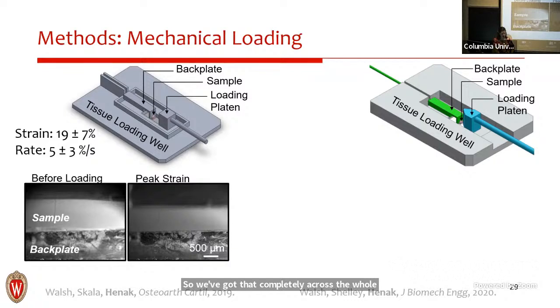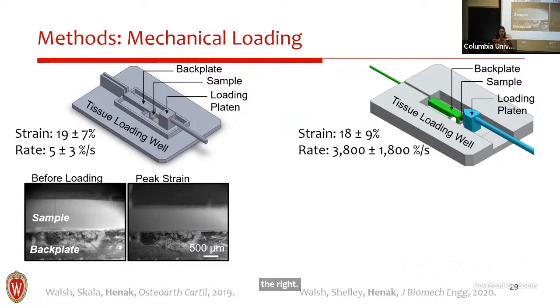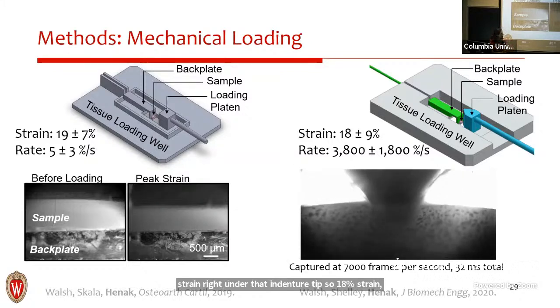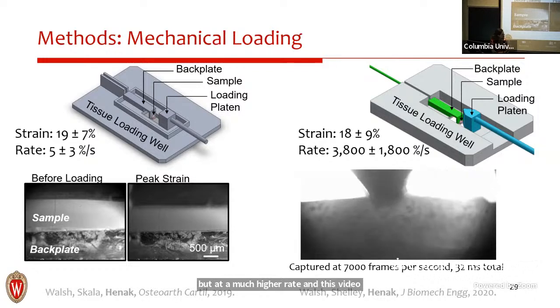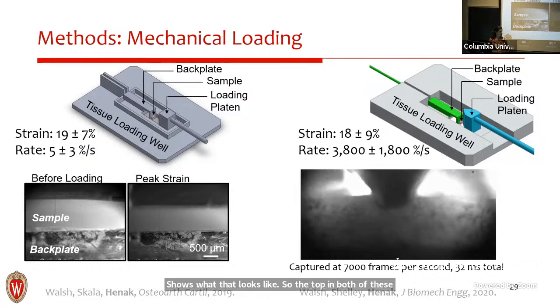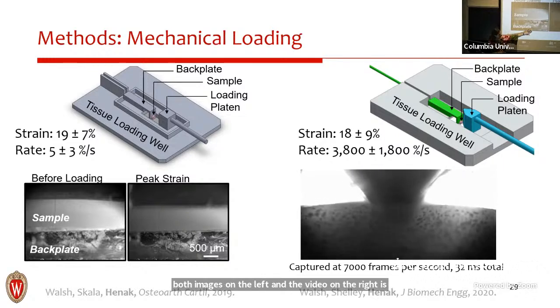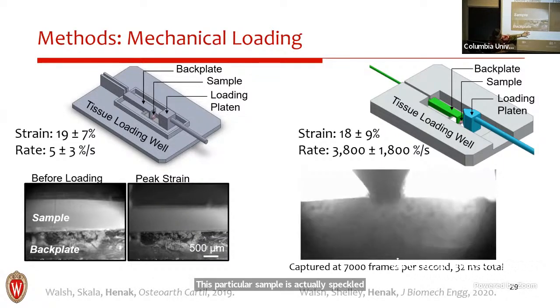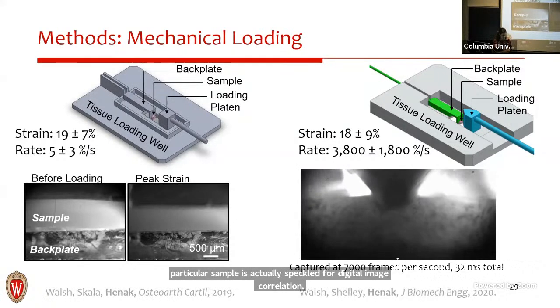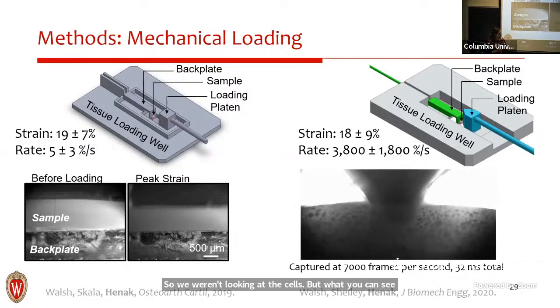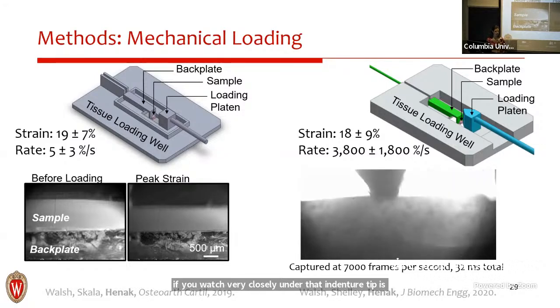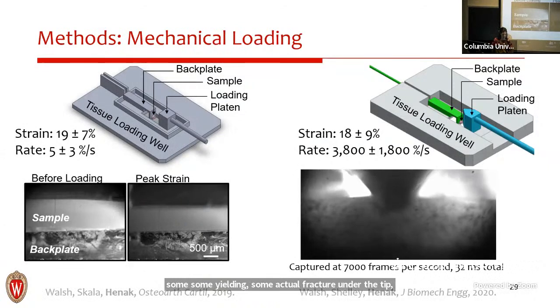On the right, we have what looks in the cross section like a sphericonical indenter, but it's a rod attached to a triangle shape. Approximately the same engineering strain right under that indenter tip, so 18% strain, but at a much higher rate. And this video shows what that looks like. So the top in both of these, both the images on the left and the video on the right, is the articular surface. This particular sample is actually speckled for digital image correlation, so we weren't looking at the cells. But what you can see, if you watch very closely under that indenter tip, is some yielding, some actual fracture under the tip. So we know we've induced some pretty good damage there.